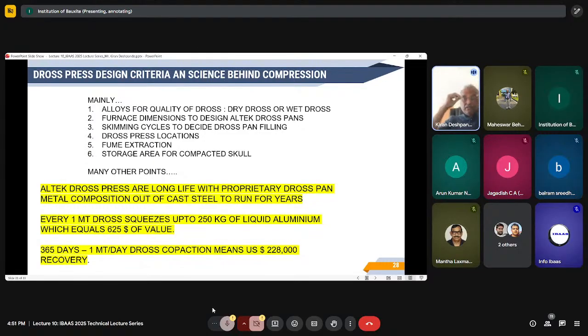Sometimes in the drossing cycle, the first drossing is where you generate more skimming, so you require a big pan. But if in the next drossing cycle your dross generation is less, then your dross pan can be reduced to a smaller size, because the dross pan should be more than 85% filled before going to compression. So these are the design aspects.